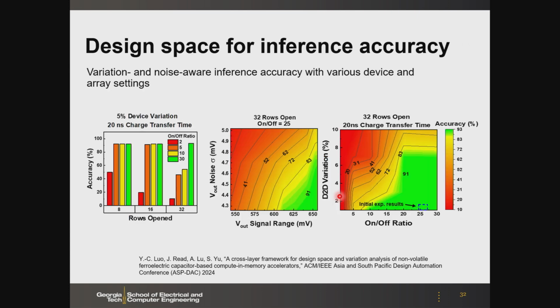So then here are some results. I quickly show you that. It's a design space exploration problem because we have so many parameters to affect the accuracy. But here, for example, you see that the on-off ratio matters. If you have on-off ratio only 2, then the accuracy will be bad. But if you improve the on-off ratio, the on-off ratio over like 13, then you can get good accuracy. And also this depends on how many rows you turn on simultaneously, and what is the op-amp output swing, and what is the on-off ratio.